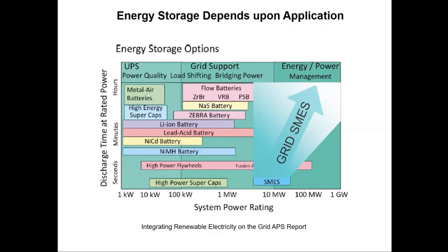Metal air batteries are in general considered for long-term energy storage applications, one of the most promising, because they are by far the most energy dense by weight. Of course, there are a lot of challenges associated with coupling air with a reactive metal, such as a lithium air battery, because lithium metal is thermodynamically unstable in the presence of air. But yet, if you wanted to build the most energy dense storage system, you would use the lightest elements possible. And that's why this ranks up above here.